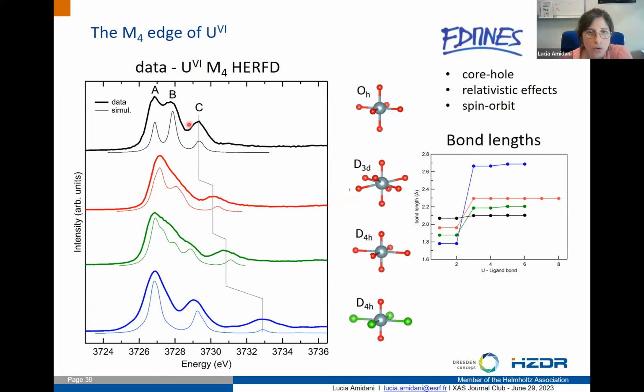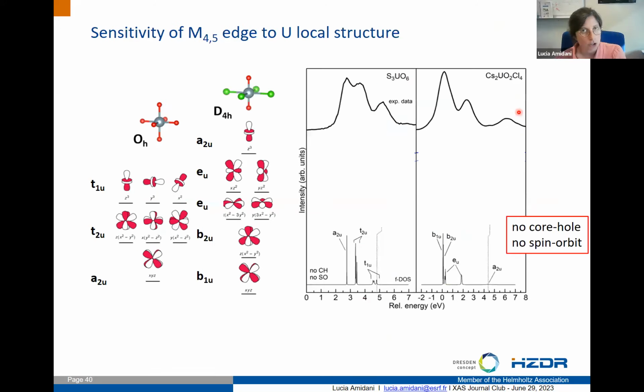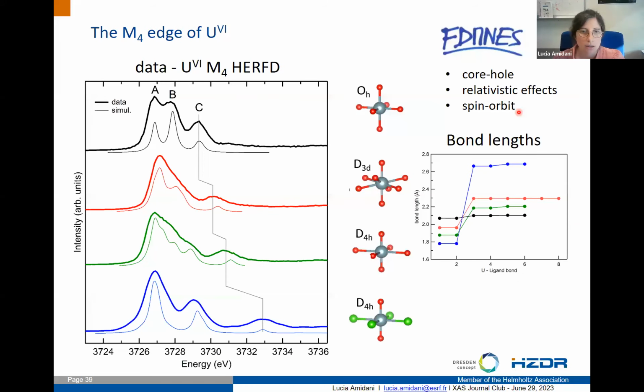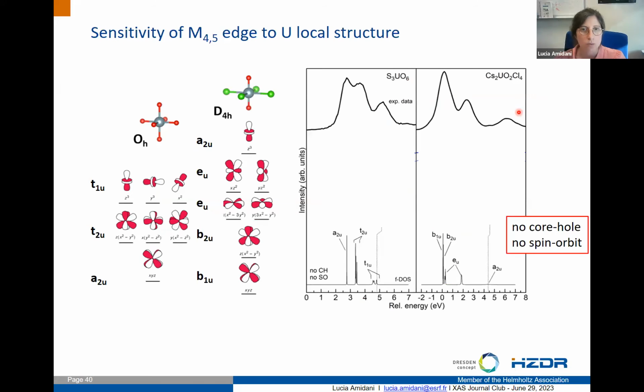Which I mean the presence or not of three features, especially the presence of this higher energy feature that is shifting towards higher energies. And let's say that the options of FDMNES that we used to get the results specifically consider the core hole and the spin orbit, relativistic effect as well, but mainly spin orbit. And when we have such a nice agreement in calculations like this, the insight into what we are observing is given by a detailed analysis of the densities of states.